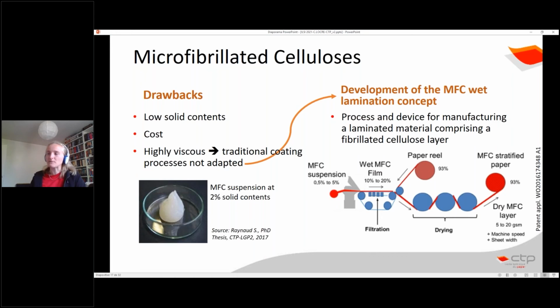And this is where the MFC wet lamination process came to life. So the idea is that the wet MFC film is formed by filtration of the MFC through a wire, and only once this MFC film is formed, then it is transferred onto a paper or board substrate, and since it is still wet, it then naturally adheres to the paper substrate. So there is no glue that is used to join the MFC layer to the paper or board layer. It's all natural adhesion, and the paper on which the MFC film has been applied is then simply dried before being rewound, and you then have an MFC laminated paper at the end of the machine.